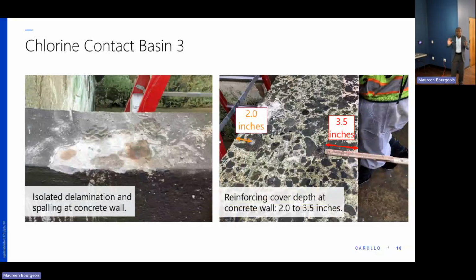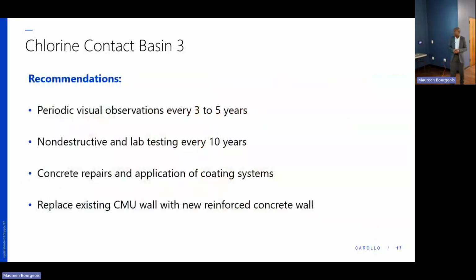So after all our analysis of the chlorine contact basin, what is our recommendation? Well, we recommend periodic visual observation, just like we did, every 3 to 5 years, just to see if the structures continue the way they are, or if they deteriorate further and need further action. Non-destructive and lab testing and in-depth study, we suggest every 10 years to be performed on the structures. And then areas where we see delamination, spalling, as we showed in the previous pictures, some of them with the acid attack and things like that,